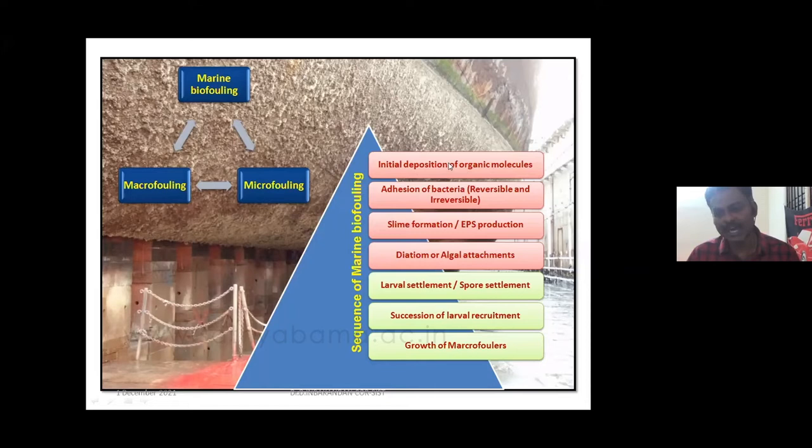Once the organic molecules have started an organic biofilm, the planktonic bacteria present in the water, which have the tendency of adhesion with the help of van der Waals force, come and stick onto those organic biofilms. Some of the bacteria have reversible adhesion, and some of the bacteria have irreversible adhesion. If it is reversible adhesion, with the flow of the water, the bacteria get loosened and will be washed away from the organic biofilm surface. But those bacteria sticking onto the surface in an irreversible manner because of this van der Waals force,